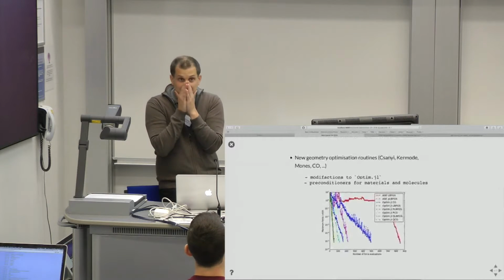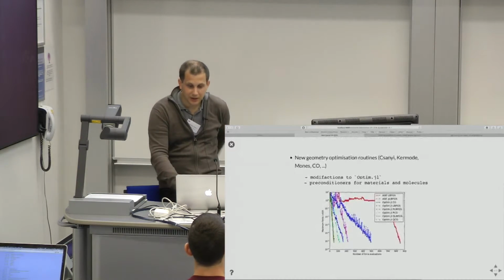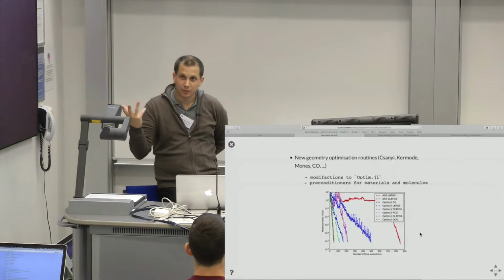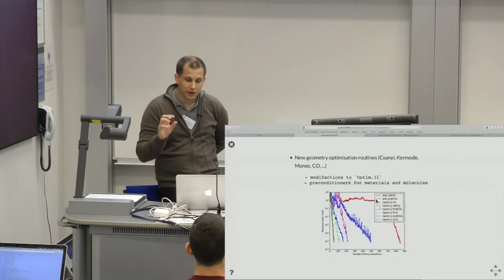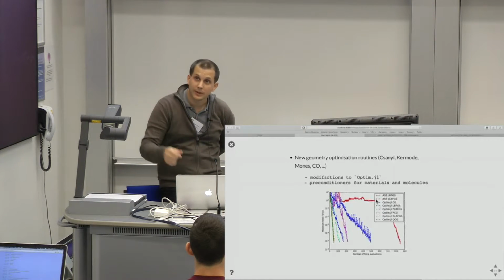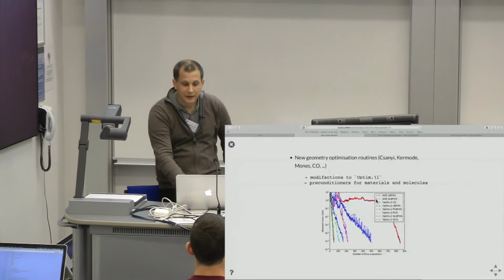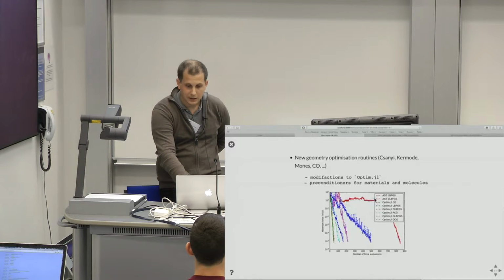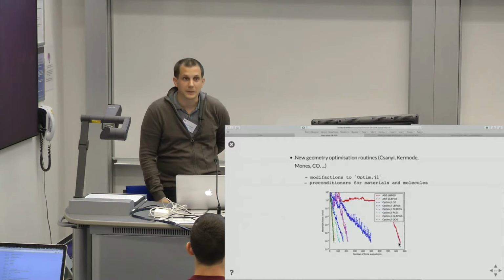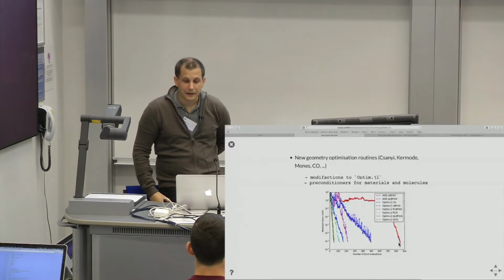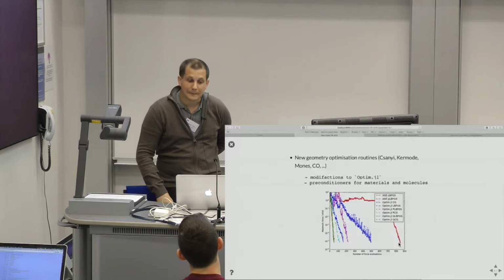One thing that we've been working on a lot is geometry optimization, and what I wanted to show you here is the Python library ASE that I mentioned, the standard geometry optimization you're using there for a very basic problem, exactly the one I implemented for you before. You have a slab of silicon, you put in a defect, and then you minimize the energy, that's the red line. Okay, so you get about 900 iterations for a very simple problem. Absolutely awful. And that's actually a standard implementation of LBFGS.